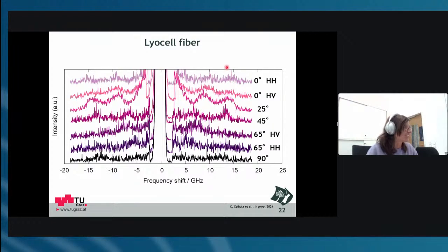Again, you can see that the spectra at different orientations are changing and getting a little more scattery. This was the issue here. But we do not see this effect of the scattering mode anymore. So there is definitely a difference between these two fibers. That's also why I'm already showing you that. You do not measure the same thing with each fiber, so you can distinguish differences.